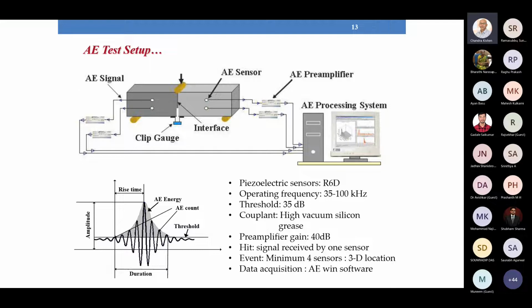All the peaks which have crossed the threshold, we call an acoustic emission count. And if the same peaks are registered by all the sensors, or at least 4 of the sensors, we call that an event. Now here an event can be physically understood as some kind of micro crack which takes place in the material. So whenever a small micro crack occurs, that will result in an event. In acoustic emission parlance, an event can be considered as a micro crack.